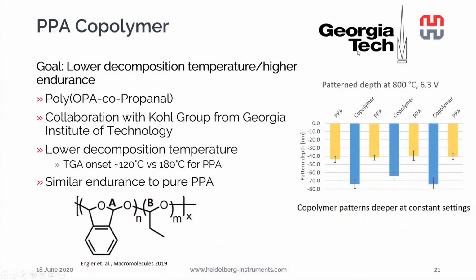One really interesting project that we're doing with the Kohl Group from Georgia Tech is to use a PPA copolymer with an aliphatic aldehyde, like in this example. This promises a lower decomposition temperature compared to pure PPA. In this example, we did thermogravimetric analysis, and instead of 180 for the pure PPA, we got 120 degrees decomposition temperature. We hope that we can actually increase the endurance of the patterning compared to the PPA. So far in the first test, it's at least similar endurance to pure PPA. But in this small graph here, we see that at the same settings, 800 degrees, 6.3 volts of force, we were patterning about 40 nanometers deep in PPA, but almost 60 to 70 nanometers deep in the copolymer. So it decomposes much more easily than the normal PPA.